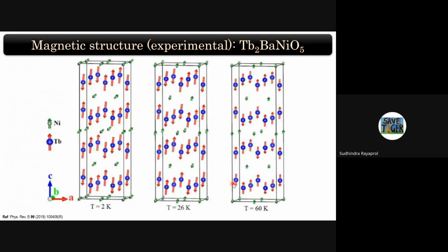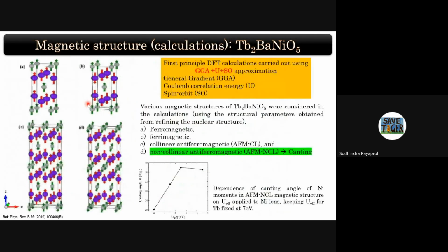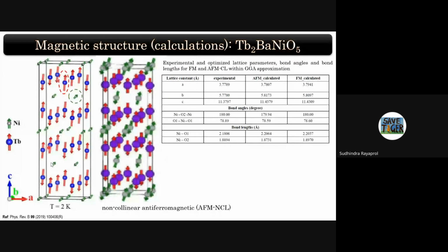So the information which we are keen to show you is the canting angle between terbium and nickel as a function of temperature. We actually calculated it using different magnetic models also: ferromagnetic, ferrimagnetic, collinear antiferromagnet and non-collinear antiferromagnet. We find that the calculation for the non-collinear antiferromagnetic cell coincides with our observed magnetic structure. And for this kind of arrangement, where the terbium and nickel moments are canted with respect to the c-axis, we find that the ground state is lowest,